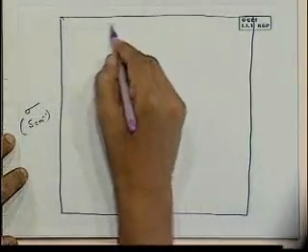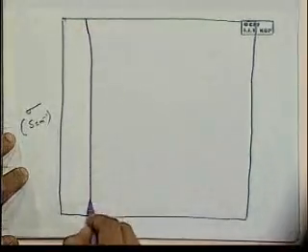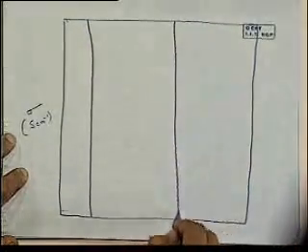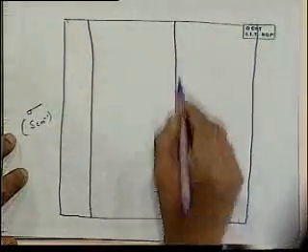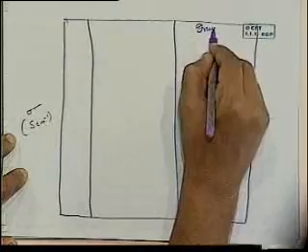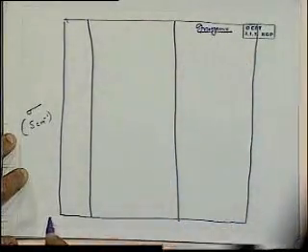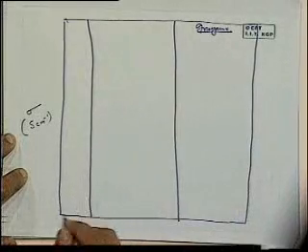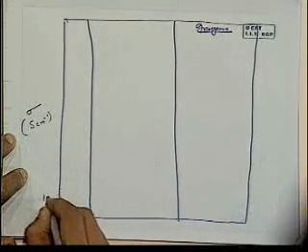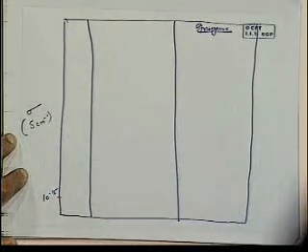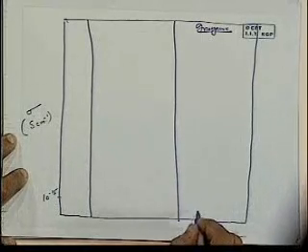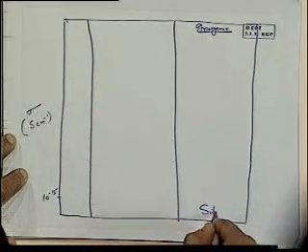On one side I will list, okay, let's put the conduction value here. I'll list some of the inorganic materials that are used over this range. So down here would be, say, our insulator category. We're talking of something like less than 10 to the power minus 15 conductivity, very insulating. And we're talking of a material like silica.